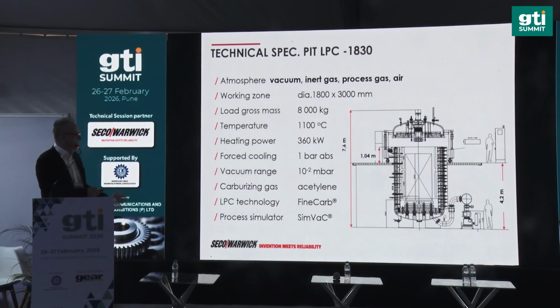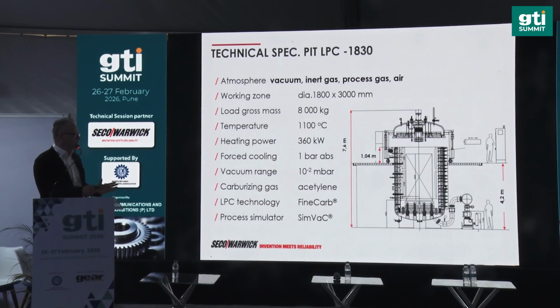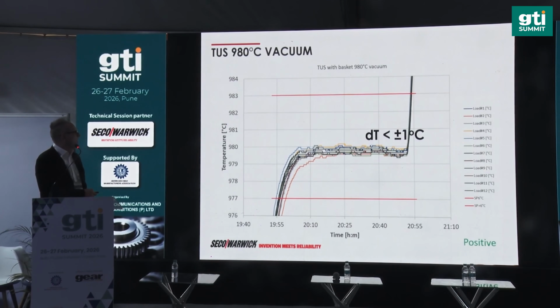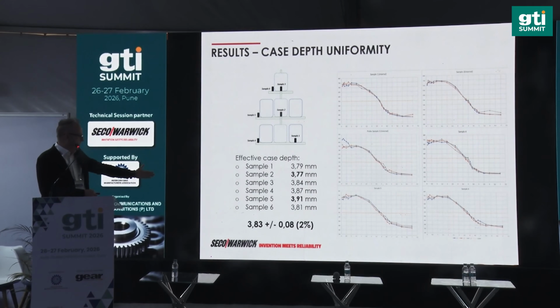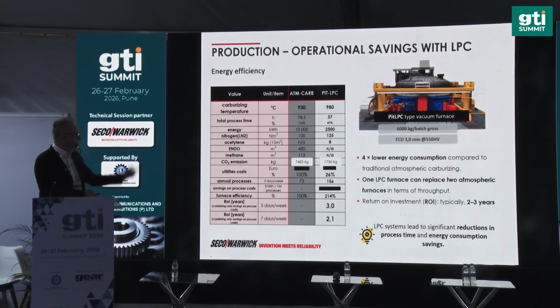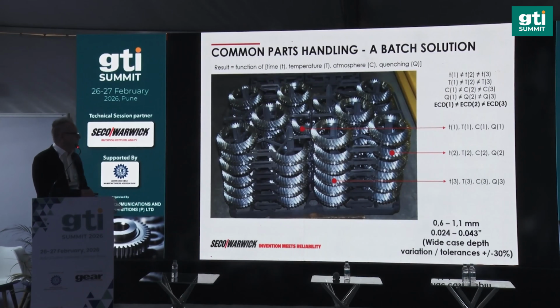Just a few information about this furnace. Actually, it can fit the same solution as you have currently in regards to the atmosphere pit type furnaces. Having the temperature uniformity within ±1 Celsius degrees, and the case depth tolerance of 0.08 mm within the several testing points within the whole batch of such a huge furnace, which gives you the information that you can drastically lower the energy consumption. In this particular case, by reducing by 50%, one furnace can replace 2 atmospheric furnaces and can return on investment within 2 or 3 years.